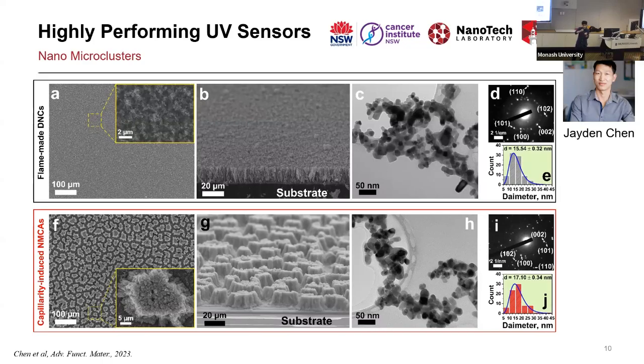If by stability you mean you have a blade and you want to scratch the surface, no, it's not. Or the pencil test, with black or HB or different levels of HB, as standard coating stability tests. The harshest scenario we tested, we had it in the water with the water circulating. Then we changed the circulation speed and pressure, and it was still okay. Yes, it's a functional coating.